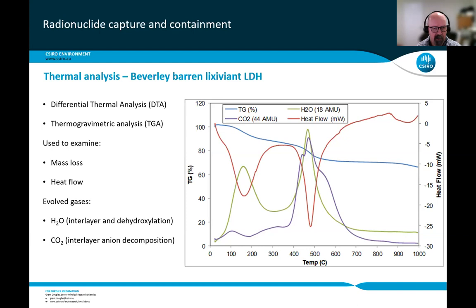Now, if you follow the green line, which is the water, you can see as you heat, you start to get a net loss of water. That green line starts to increase up to about 100 and 200 degrees. And that is the loss of the waters of hydration, as you may have seen earlier, that are present in the interlayers of the layered double hydroxide. But then when you start to heat it up further, this sample, between about 400 and about 600 or so degrees, you then actually have a dehydroxylation reaction. So you remember the metal layers, there are metal hydroxide layers. So you actually start to dehydroxylate those.